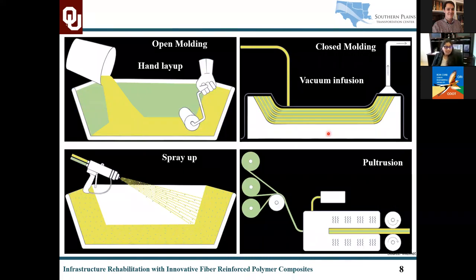Some of the different processes can help us understand better what kind of innovations can be brought. First and foremost, this open molding process for FRP systems, which is a hand layup, where the fabric is impregnated by rolling the resin on top of it, enabling impregnation of the resin into different layers of the FRP. Following the hardening and curing process, it offers a high strength composite sheet that we can see using the hand layup.